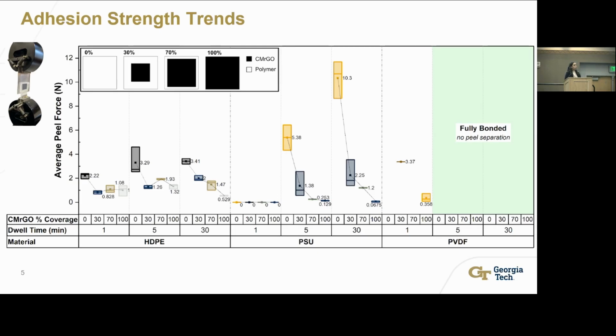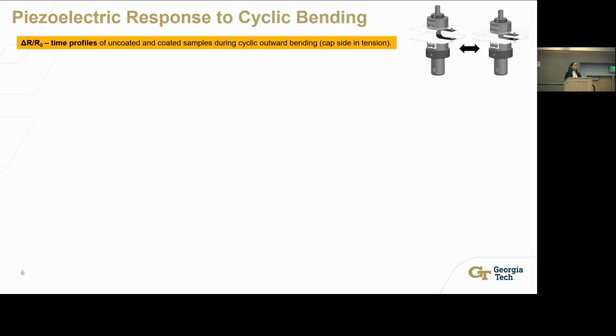overlap area. Now, what we have observed here was as expected, with longer dwell times and fewer particles at the interface, we got better adhesion. But what stands out is the green region on the right with the PVDF material category. We've actually got no peels, showing a strong adhesion and fully bonding case.